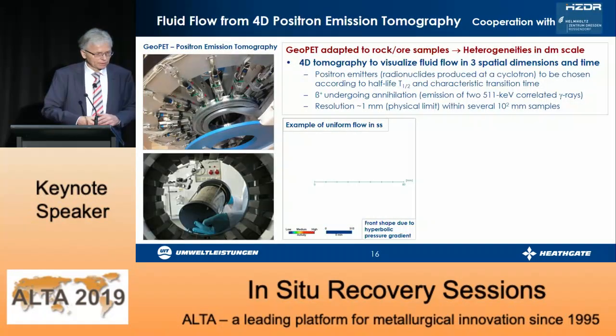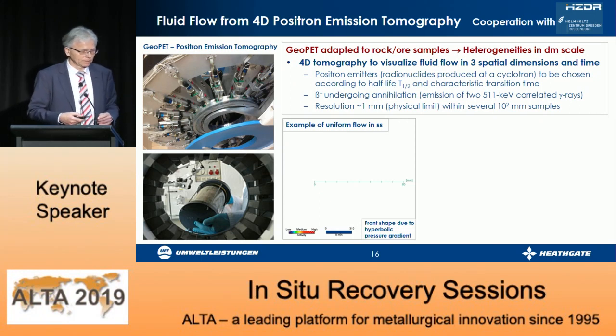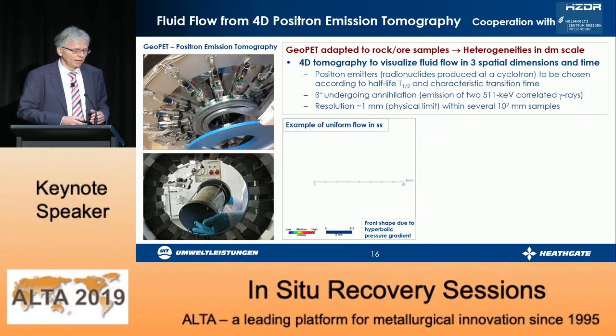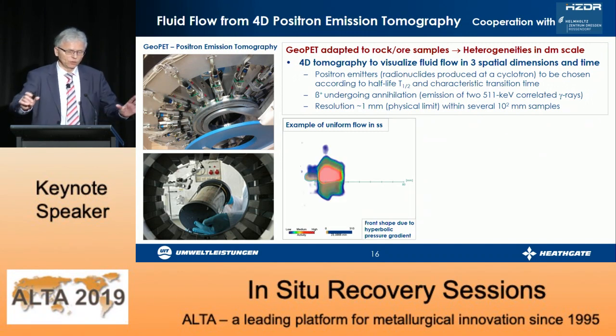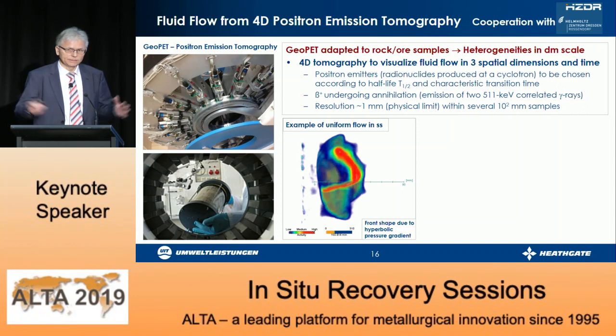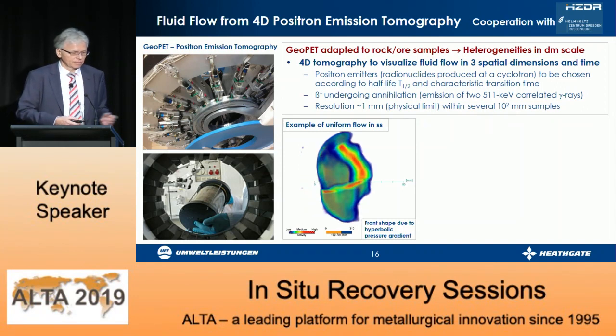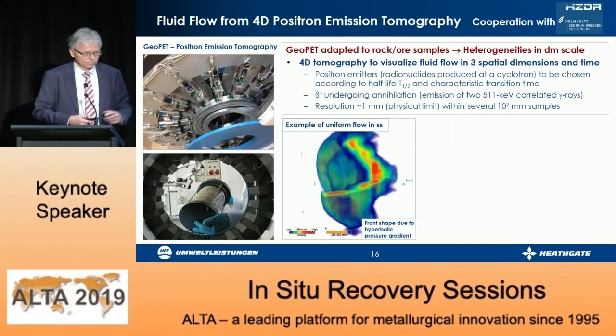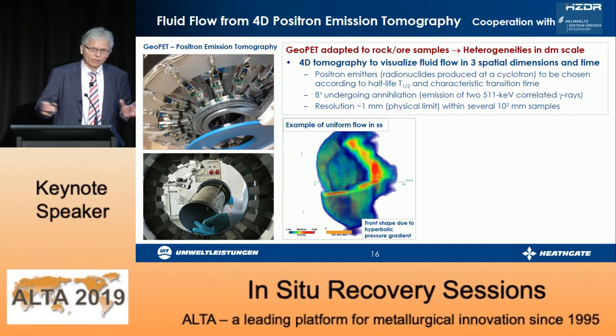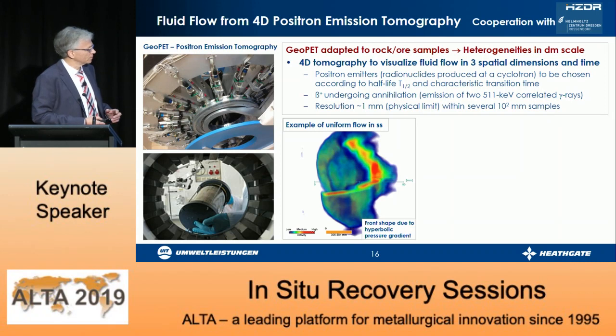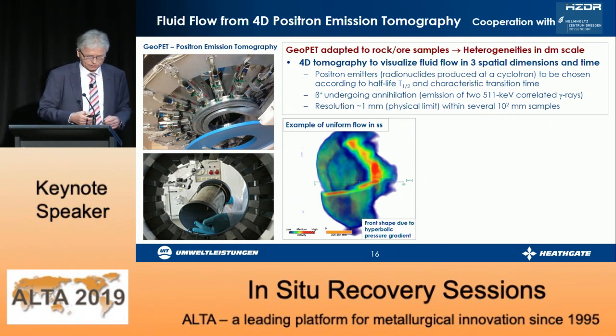A next example is the application of positron emission tomography. That means you dope the injected fluid with radionuclides, and you visualize the fluid flow on a coarse, decimeter scale. This is an example shown in this image, where we have a quite uniform flow through the core sample. The front shape is due to the hyperbolic pressure gradient in this particular case.